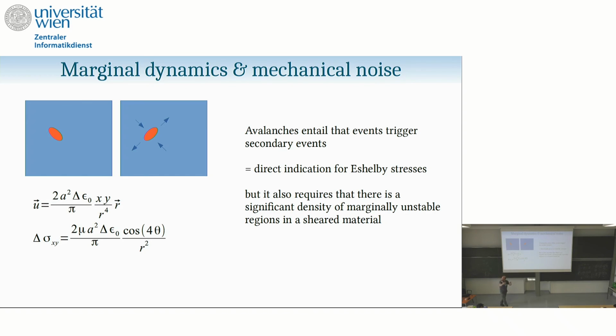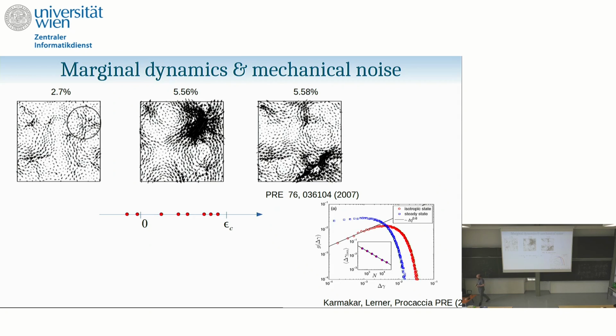So you bring your system into a marginal state where you are feeding in a population of near-threshold zones. Then when one event triggers, you have this elastic field, that Eshelby field, that propagates, and it will trigger secondary events, and that's how you get an avalanche.